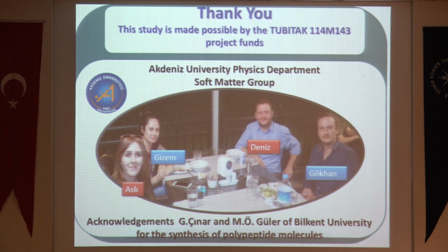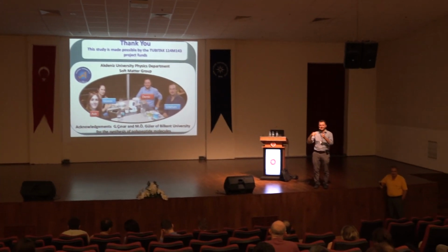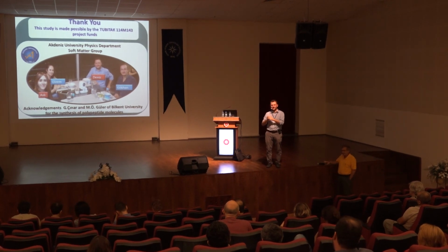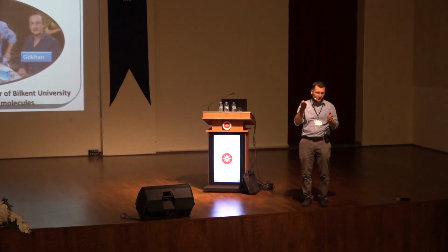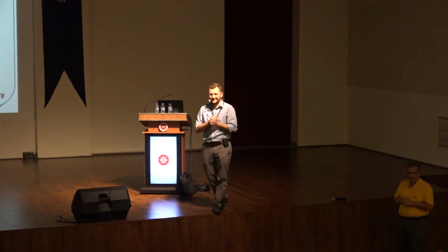Well, no. Actually, in a viscous medium, like a fluid, you will get x squared proportional to t. But in a viscoelastic gel network, it has to be in the sub-diffusive regime, which is t to a power less than 1. This is what we have seen in our gel, and that's why I mentioned the Langevin equation, the solution for that, how you can get from the MSD to the G parameters, which we are doing by fitting and trying to get to more complex behavior, which you already know. Yes. Yes.